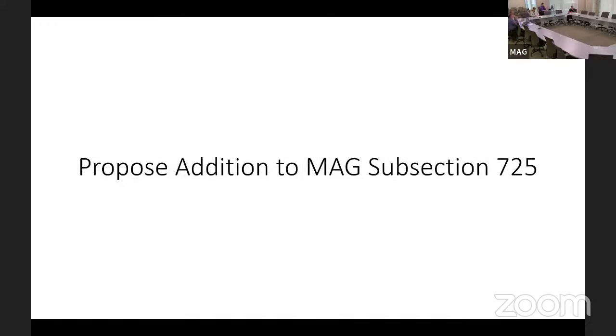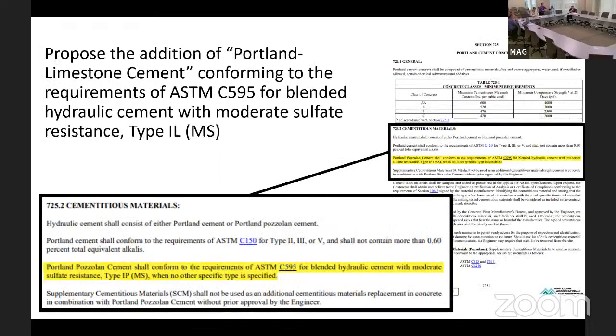So the proposed addition to the MAG subsection 725, the next slide here. Up on the right is the current 725 verbiage. We blew it up there. As you can see, you currently accept ASTM C150 type 2 moderate cement, type 3 high early, and type 5 high sulfate. Also, you currently accept a C595 IP cement, which is a blended pozzolan similar to a blended limestone. So very similar cements are already accepted.